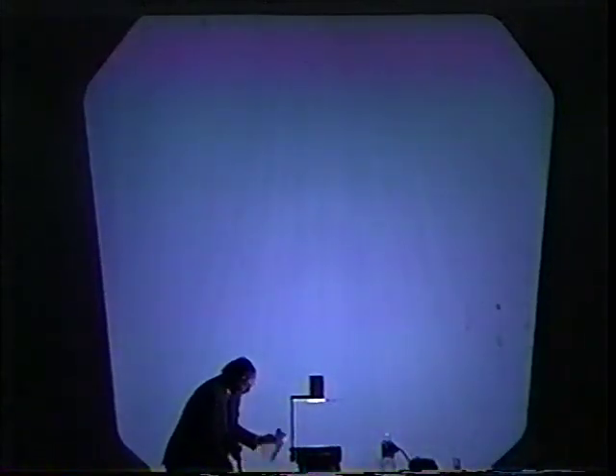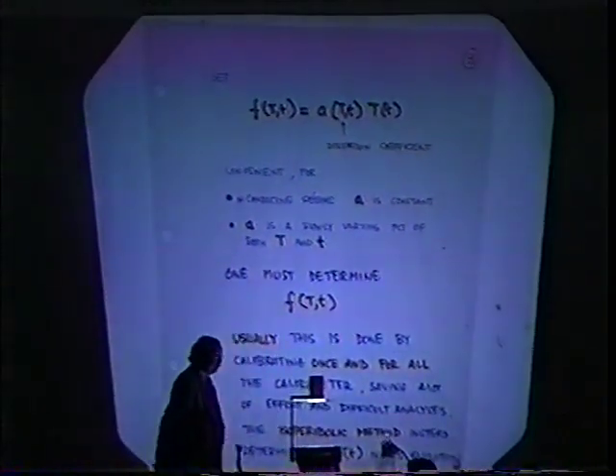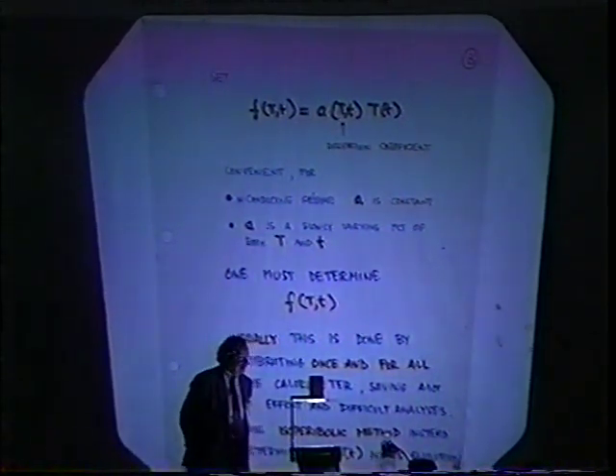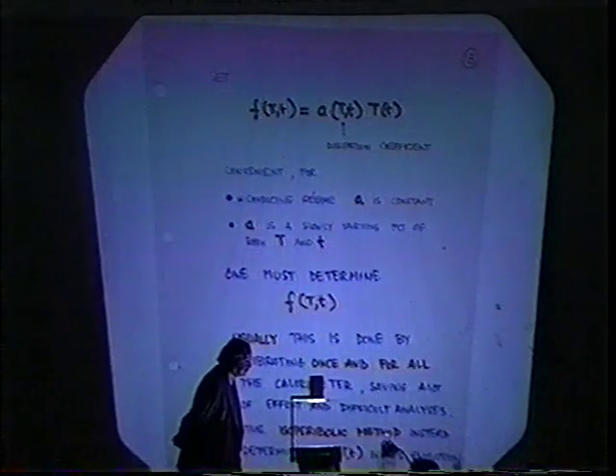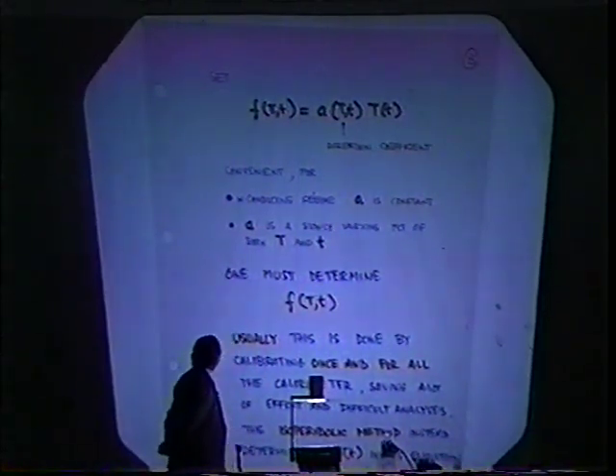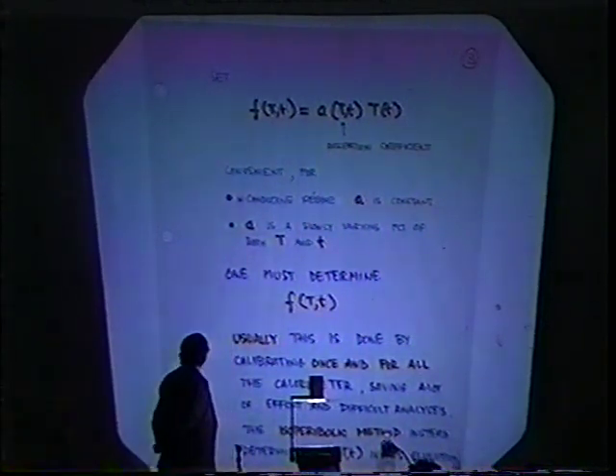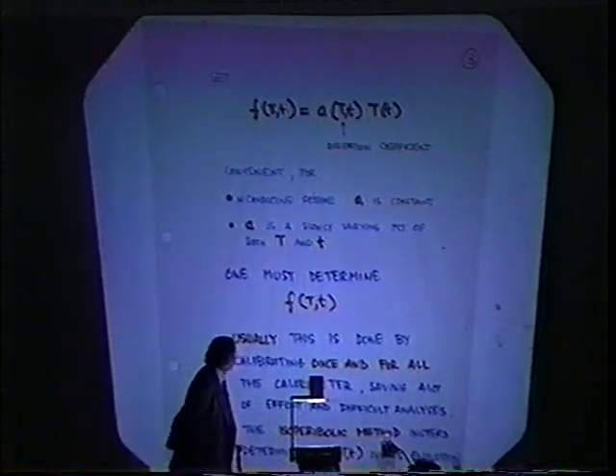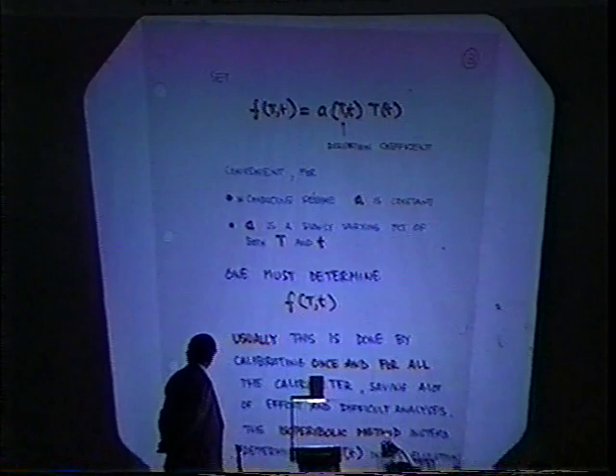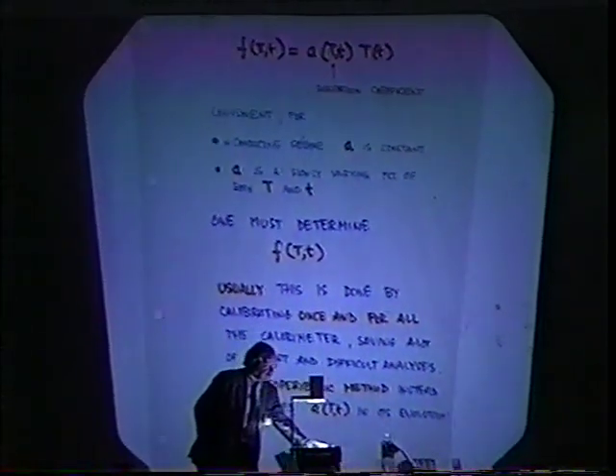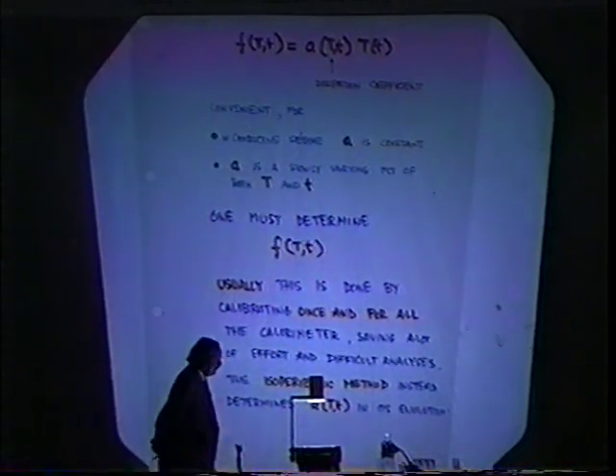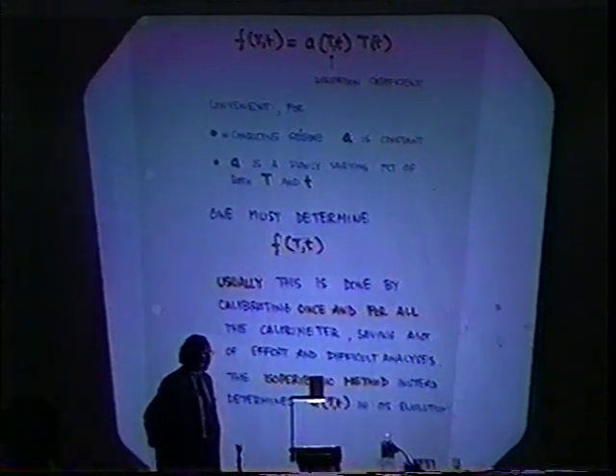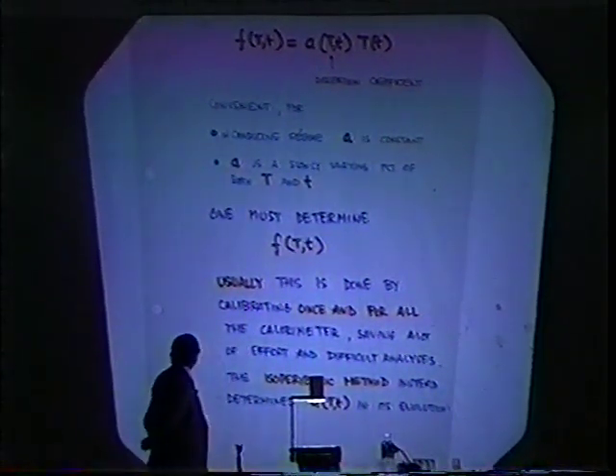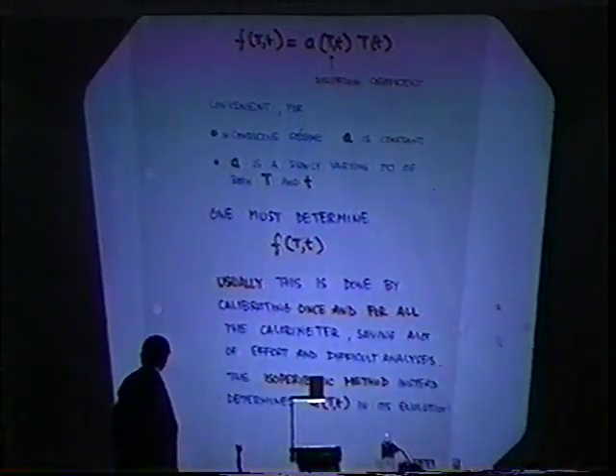I will not make any assumptions on the dissipation function. However, due to the fact that in my cells I'm dominated by conductive dissipation, I just write the dissipation function in that form, which I always can, of course. This is convenient because in the conductive regime A is almost constant, and A, in fact, is a slowly varying function of both T and time. Then one must determine this function in order to get a determination of the excess heat, of the power which is developed in the cell, in the calorimeter.